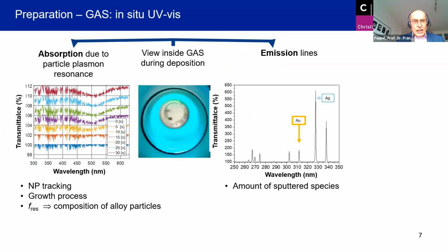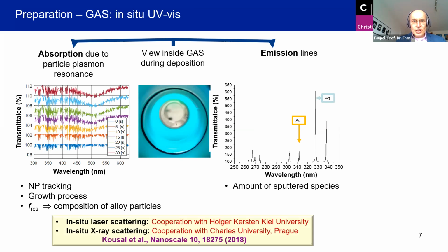In order to tailor the particles, we need in situ capability to monitor the growth of the particles. This we do, among other techniques, by UV-vis spectroscopy. Here are typical examples of silver and gold lines, which give us information on the amount of species in the gas phase. But we are also able to observe in situ the growth of the particles, for instance, by observing the evolution of a plasmonic peak, which is particularly interesting for alloy particles. In order to tailor particles, you need not only monitoring, you also need in situ control. But before I come to in situ control, a few words also about monitoring.